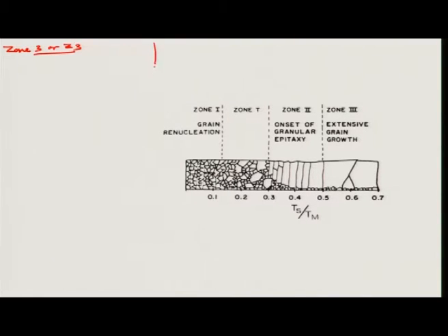In zone 3, the conditions for evaporation are Ts over Tm of 0.5 to 1, so very close to melting temperatures, and for sputtering it is Ts over Tm of 0.6 to 1. So, very close to melting temperature, very high surface diffusion. We are not melting it, it is just close.